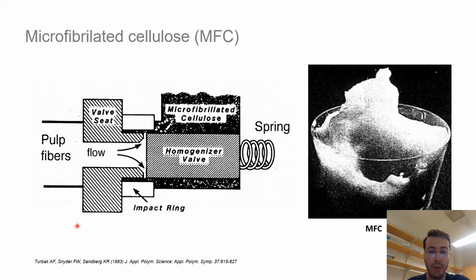The story of MFC goes back to the early 1980s, where for the first time Albin Turbak and his co-workers were trying to homogenize a water suspension of bleached pulp fibers with very low amount of lignin, and after several rounds of high pressure homogenization they got a gel-like whitish material, and they called that MFC, or microfibrillated cellulose. Since then, most of the research in this area was focused on bleached samples with low amount of lignin.